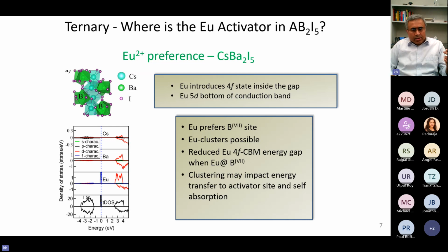Anyway, in this structure, the interesting thing is the barium site, the site right there. There are two distinct crystallographic sites where barium can be located. Let's call them barium 7 versus barium 8. I say it like that because in one site it's coordinated with 7 iodine atoms, sorry, not chlorine. The halogen is the iodine atom. At one site, it's coordinated with 7 nearest iodine atoms, so we call it the B7 site or barium 7 site, and the other is coordinated with 8, and we call it B8 or barium 8.